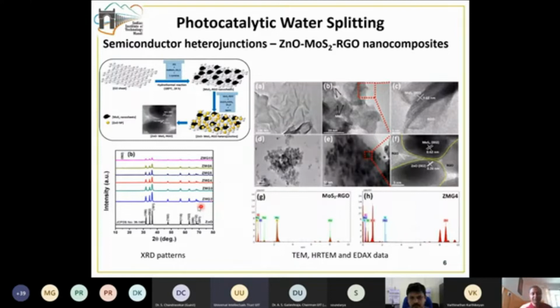For example, when we take this 2 weight percent, it means that 98%, the majority, is zinc oxide, because this is the active semiconducting material in our case. And then the remaining 2% is distributed between MoS2 and RGO. And since the composition between MoS2 and RGO is 1:1, there is 1 weight percent of MoS2 and another 1 weight percent of RGO, in this case ZMG2. Whereas when we take this ZMG4, it would be 96% of zinc oxide and 2% of MoS2 and 2% of RGO. Similarly, we prepared the other compositions as well.